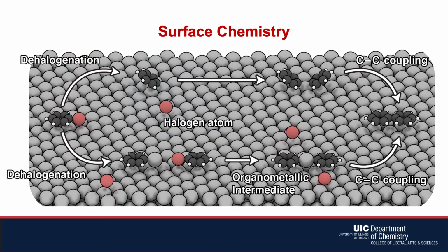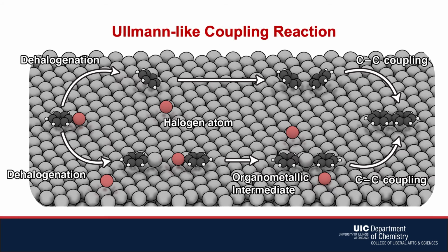When the interactions between molecules and a substrate are substantially strong, the surface can be used to catalyze chemical reactions. In the Ullmann-like coupling reaction, aromatic precursor molecules containing aryl halides undergo dehalogenative coupling reactions via thermal activation on a metal substrate, yielding atomically precise nanocarbon structures. Although a leaving group, the halogen atoms can remain adsorbed on the surface and are typically considered to be an undesirable byproduct that can poison the growth process of nanostructures.